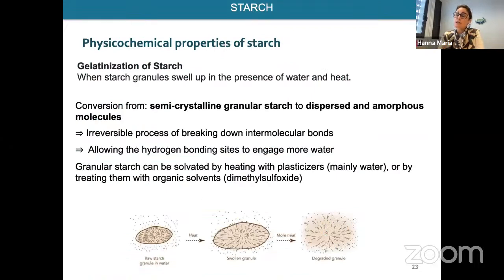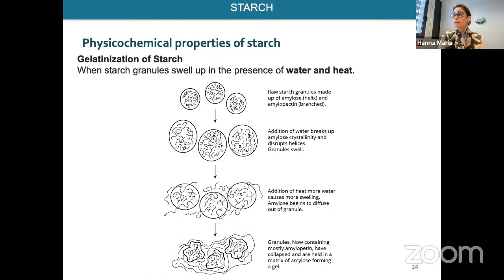The gelatinization of starch, like the name gives us an idea, we will make a gel from starch. The most important physical thing that happens is that the starch granules swell up in the presence of water and heat. It's the conversion of the semi-crystalline granules of starch to dispersed amorphous molecules. This process is irreversible, because it's breaking down some intermolecular bonds. We can do it with water, which works very well, but we can also use some organic solvents.